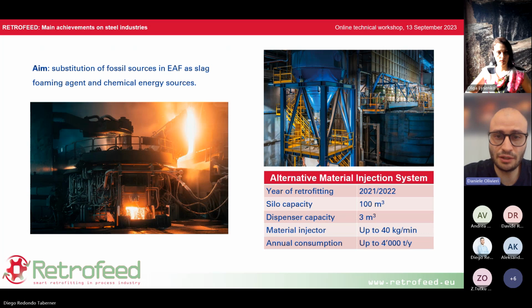On the right part of the slide, we can see our injection system, which was retrofitted over almost 2 years, 2021 and 2022. It has a material capacity of over 100 cubic meters with a dispenser of 3 cubic meters that allows us to inject the material into our furnace. And we have a flow rate of up to 40 kilograms per minute. It can also vary depending on the material. And we have an average annual consumption of up to 4,000 tons of material per year, and it depends, of course, on the material that we are using. We can go on.